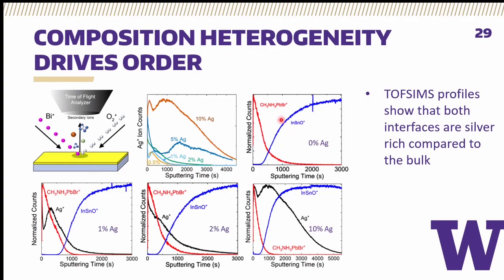methyl ammonium lead bromide and the indium tin oxide, silver counts started to spike pretty amazingly. This was irrespective of the amount of silver in our precursor solution, showing that however much front surface segregation we had with the silver, we had even stronger back surface segregation of the silver, showing us somewhat convincingly that we were indeed getting silver to segregate to interfaces and not incorporate into the bulk, but in so doing, changing the relative surface energy of 001 facets relative to other facets and driving uniform texture in our thin film through this surface energy anisotropy.